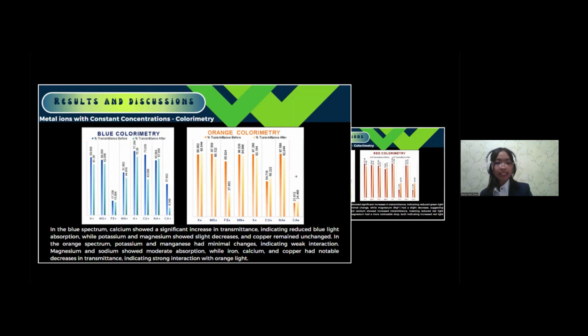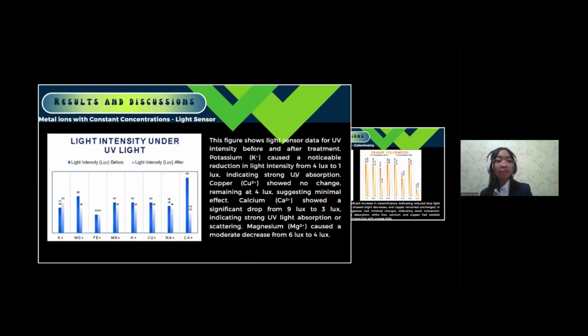For this next analysis, it tests the light intensity change with different metals, making use of the NeoLog Logger's light intensity sensor. For potassium, light drops a lot from 4 lux to 1 lux, meaning potassium blocks or absorbs a lot of UV light after treatment. Copper doesn't change the light at all, staying at 4 lux, so it doesn't affect the UV light much here. Calcium causes a big drop too, from 9 lux to 3 lux, showing it absorbs or scatters a lot of UV light. Magnesium causes a small drop, from 6 lux to 4 lux, meaning it absorbs some UV light.